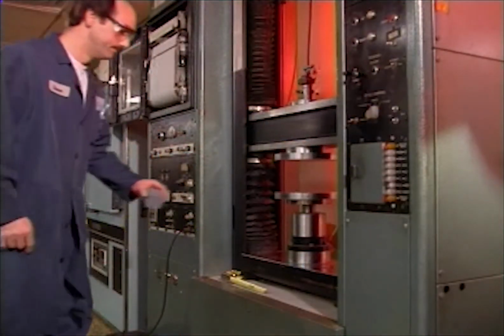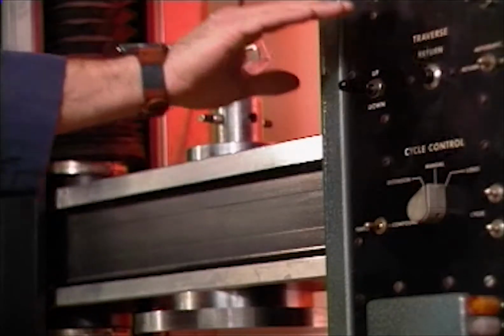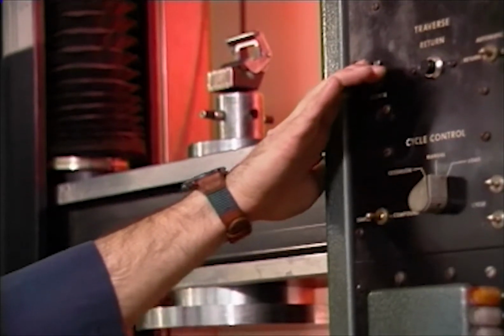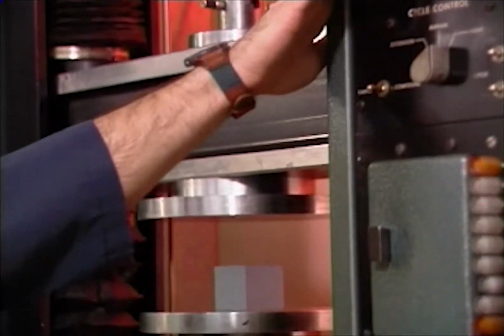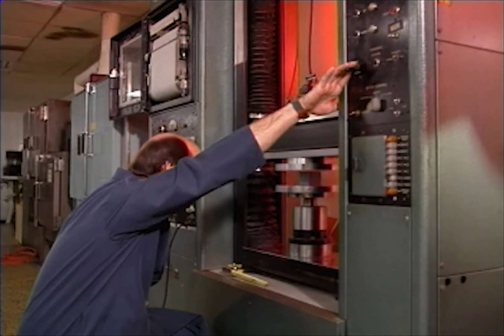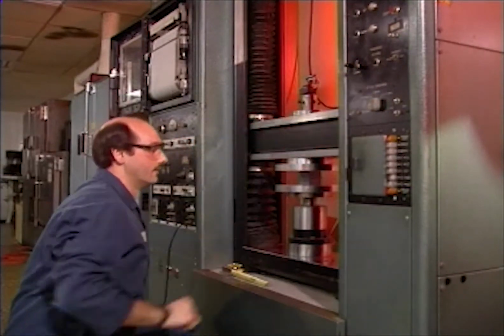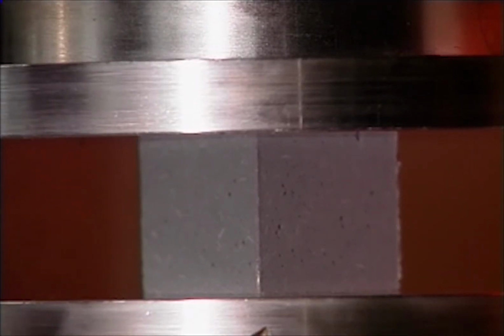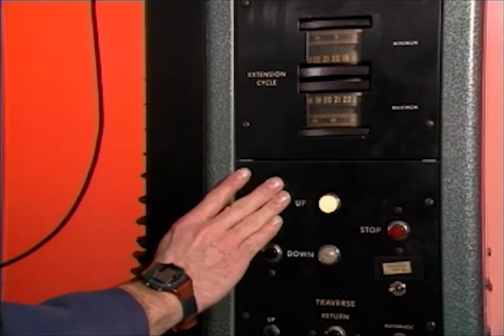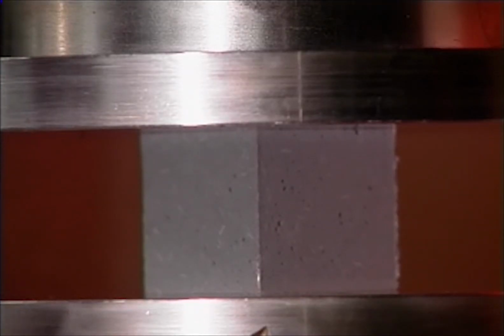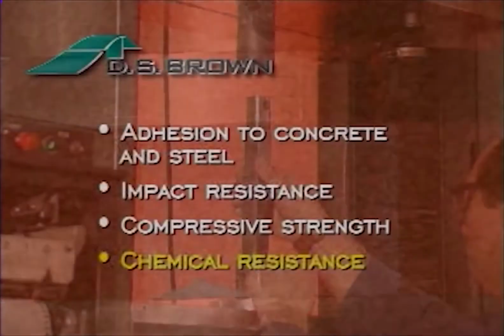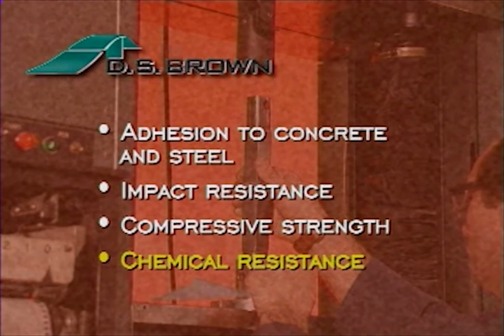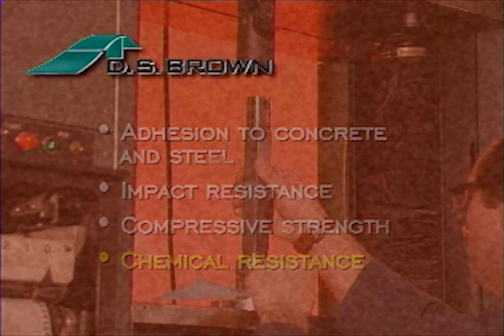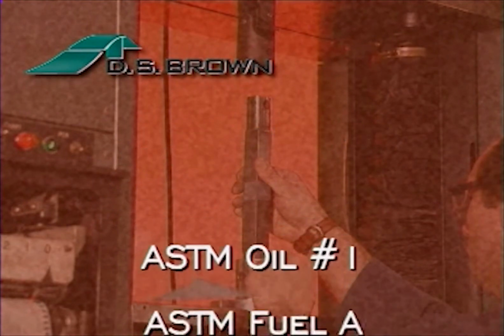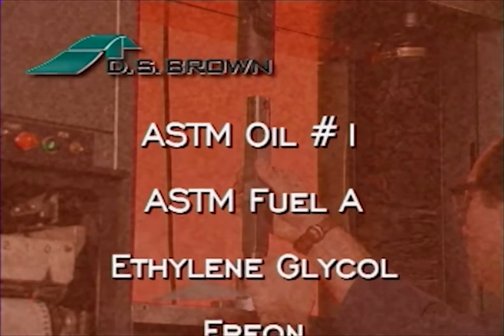Using 2-inch cubes, the compressive strength of Delpatch is measured on a laboratory Instron machine. The force to deflect Delpatch 5% is 1,100 psi, and 1,500 psi for a 10% deflection. After the force is removed, the cube recovers essentially to its original height. Delpatch is resistant to these chemicals, as proven in laboratory testing.